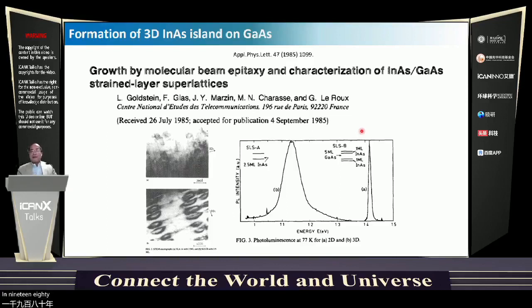In 1985, the Cnet group in France discovered the Stranski-Krastanov growth mode accidentally when they tried to grow indium arsenide/gallium arsenide strained superlattice structures by molecular beam epitaxy. And they observed defect-like islands. They are very smart, and they found that the islands are coherent structures exhibiting a bright luminescence. Since then, many groups started to work on these self-assembled quantum dot structures.